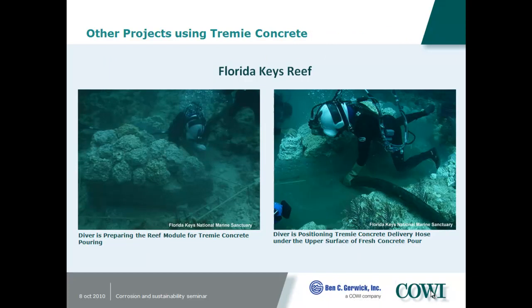Here's another example that uses a fair amount of anti-washout admixture. We consulted on four jobs like this in Florida, where ships would hit a reef, and the reef is only alive on the surface. So it's dead on the surface after it's been collided with. They wanted to come up with this tremie concrete to repair the cavity so the reef could go on growing and not die away.